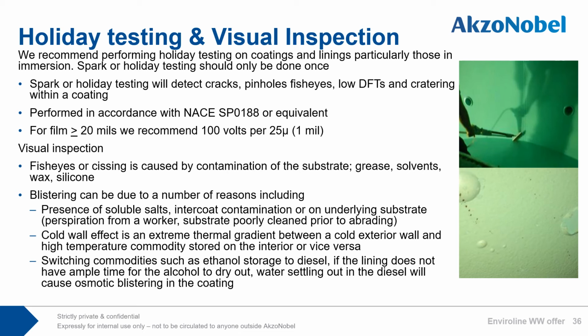Visual inspection, as we discussed in the prior slide: you may find fish eyes or cissing caused by contamination of the substrate from grease, solvents, wax, silicone. Blistering can be due to a number of reasons, including presence of soluble salts, intercoat contamination, or contamination on the underlying substrate, such as perspiration from a worker, or the substrate being poorly cleaned prior to abrading. Cold wall effects, where you have an extreme thermal gradient between a cold exterior wall and elevated temperature commodities stored on the interior, or vice versa.